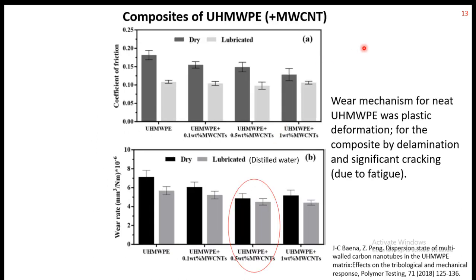So for example, if you look at the literature on UHMWPE composites, here's Multiwall CNT added to UHMWPE. Wear rate has gone down, and friction coefficient has also gone down in dry condition as well as in lubricated condition. This gray one is for lubricated, where they used distilled water as a lubricant. Here I should say what kind of lubricant we can use.